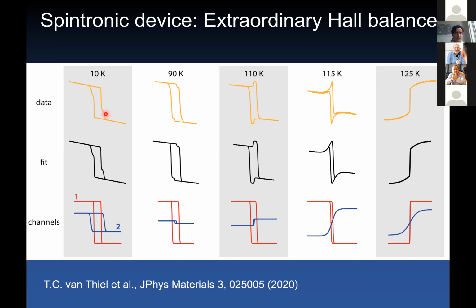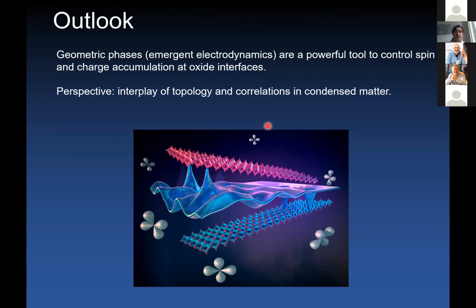So this is the data that we acquire at different temperatures, in which you realize different configurations of your spin arrangement, and these are the fits of this data using this particular arrangement for the channels as a fitting parameter. Okay. So you might be tempted when you see something like this to think of the topological Hall effect, but we believe that this effect can also be explained by band topology.